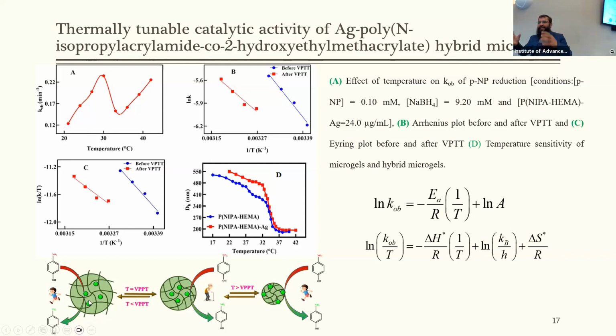When we increase the temperature, the microgel system shrinks. As a result, diffusion of reactant molecules to the catalyst surface becomes difficult. That is why the rate constant decreases at a particular temperature that is associated with the volume phase transition temperature of the microgels. However, after the volume phase transition temperature, these nanoparticles may be exposed on the surface and the rate of reaction again starts to increase with increasing temperature. So the deviation from Arrhenius behavior is actually associated with the volume phase transition temperature of the microgel. So by using temperature responsive hybrid microgel, we can tune the catalytic activity of the hybrid microgel system.